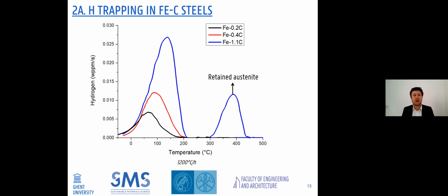This was proven by XRD measurements before and after the TVS, but also by DSC measurements, where phase transformations that take place can be recorded, and that can result in a peak, which is related to the energy that is required for the dissolution or formation of a specific phase. So this is then a proven result that retained austenite was responsible for the high temperature peak for the blue material. Not from deep trapping, but because retained austenite decomposed during the temperature ramp.